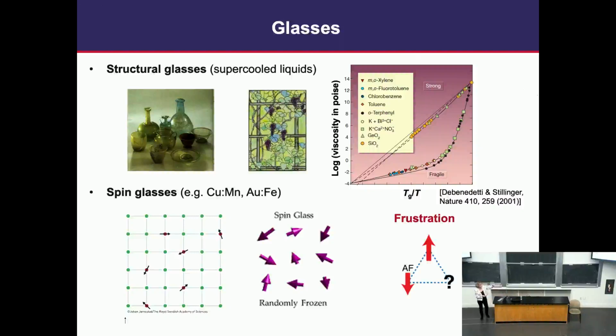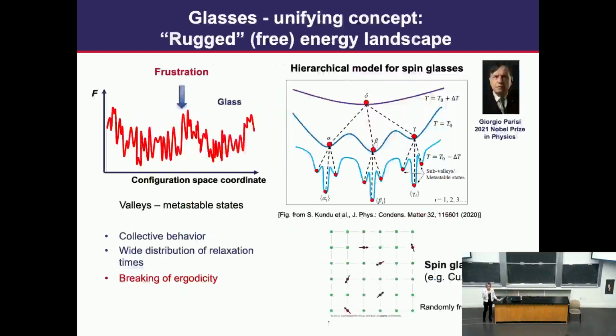So obviously these materials have a very different microscopic picture. They're very different materials, but phenomenologically they behave in the same way. And why is that? Well, this was a big problem for a long time. And it turns out that what all glasses have in common is frustration. So the free energy landscape is, they say, rugged. It has many metastable states with similar energy. Each metastable state corresponds to a particular configuration of the system.